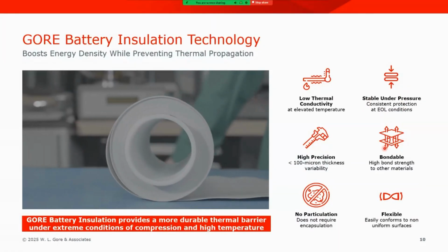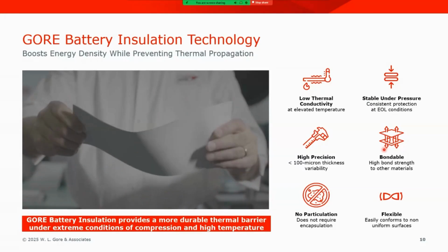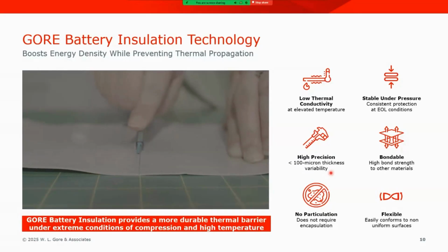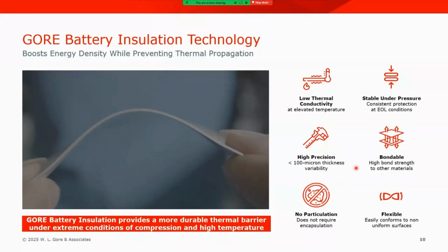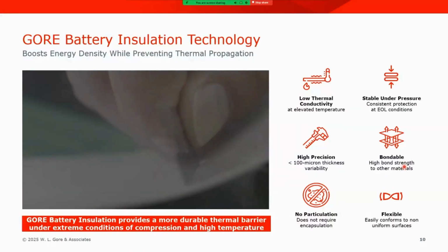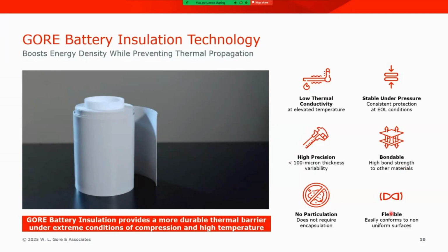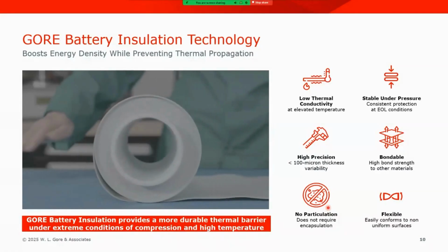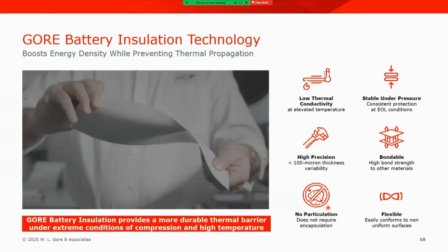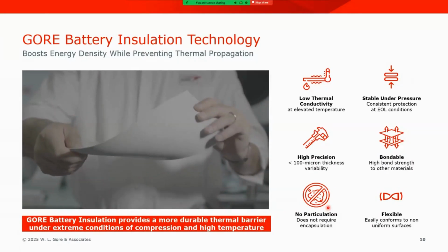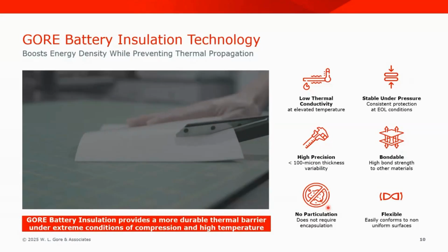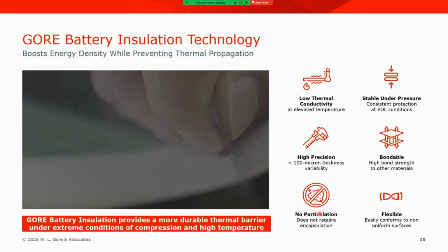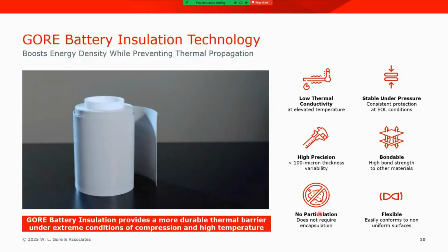As shown here in the video, we can produce this in tape form to very high precision, to within plus or minus 100 microns of variability. And as also shown, it's bondable. It can be adhered using adhesives. It's flexible, bendable, and it is very, very low particulation. If you see here in the video, at one point, we're scraping the material with a razor blade, and very little particulates come off. And so it's basically made for manufacturing. And GORE battery insulation then provides a more durable thermal barrier under the extreme conditions of compression and high temperature based on all of these properties.